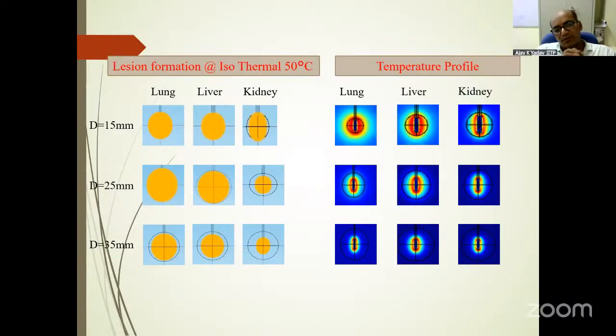For lesion formation, there are different techniques to find it. One way is, if the temperature of the tissue reaches 50 degrees Celsius, then we can consider that a lesion is formed, not 100% damage, but lesion formation. Wherever the area reached 50 degrees Celsius, if you mark it, then based on that we have put the lesion formation volume, or area in the 2D geometry. So kidney always has a smaller area, and lung and liver have more area.